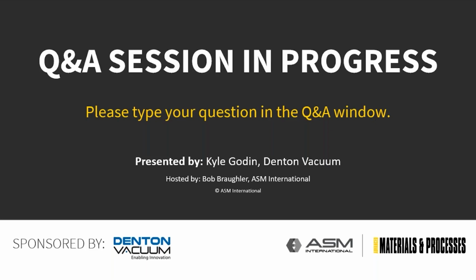Okay, our next question is, what area is the SIMS signal coming from? So the SIMS has, just because of the way the head is designed, an aperture, and also there are 2 voltage plates that steer the ions into the head. The reason for that is that, compared to a typical metrology SIMS, there is so much material coming off of the piece that it would quickly coat the entire inside of the SIMS and make it non-operational. So that aperture and those voltage plates dramatically reduce the amount of ions actually coming into the head, and they also provide this sort of directionality.